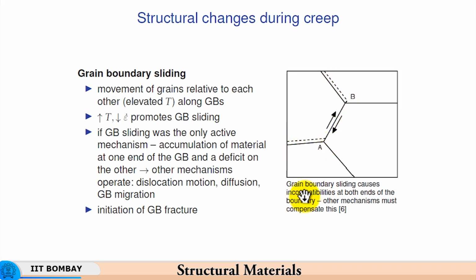So, that is the kind of process. So, that is the reason why diffusion becomes the rate controlling process. So, the creep rate depends upon the rate of diffusion. Now, if you take materials like tungsten, refractory alloys like tungsten rhenium or molybdenum tungsten and so on.